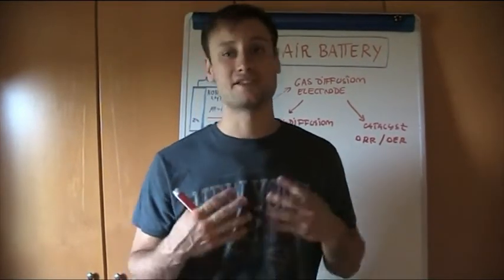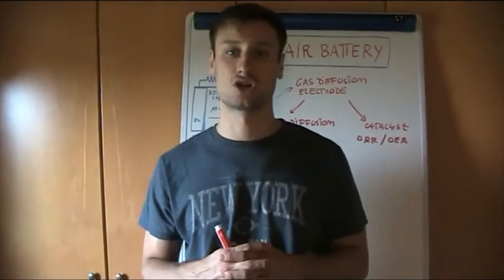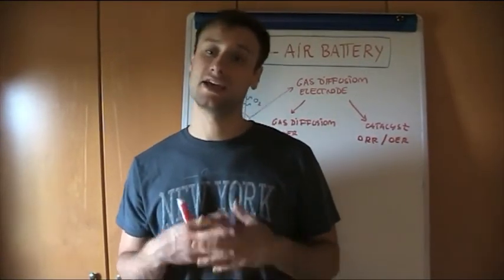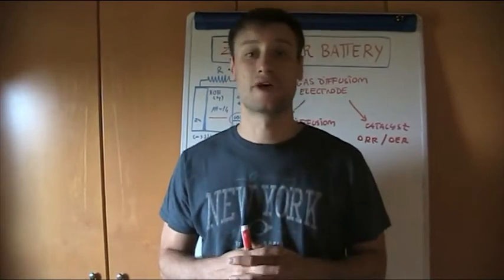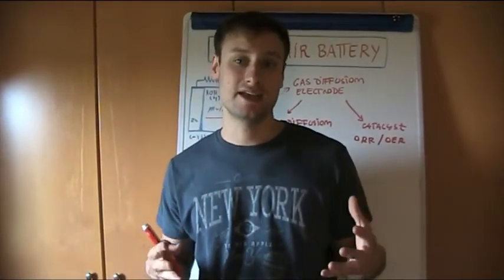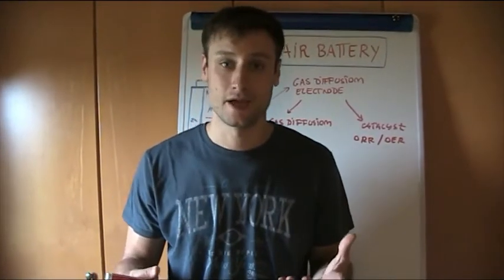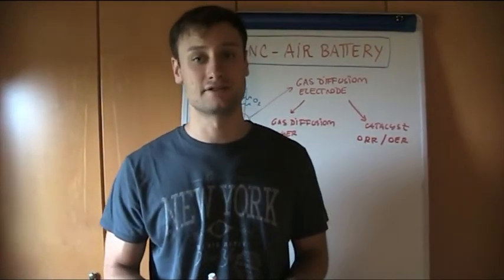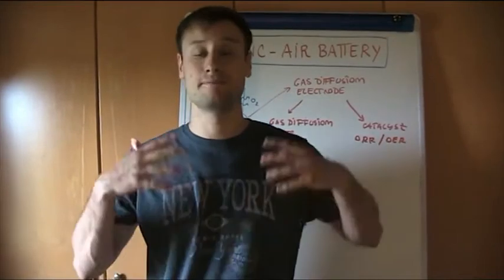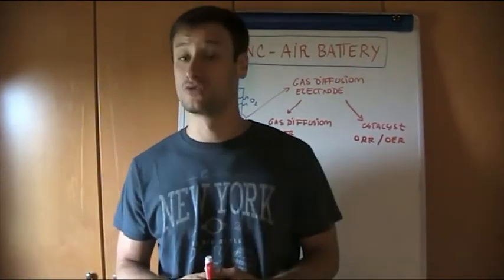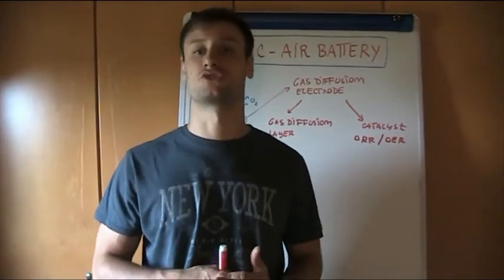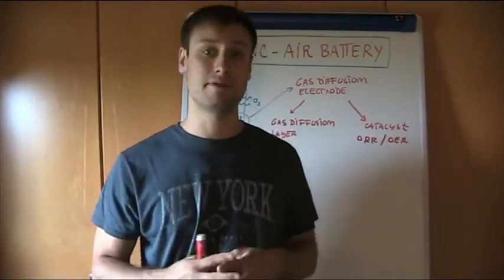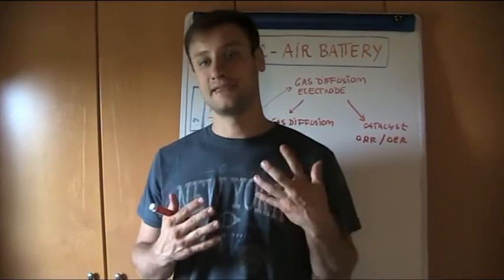And sometimes we can even see the use of Teflon, tetrafluoroethylene, as a binder, because in this way we are improving the hydrophobicity. So we are using something that is carbon-based, but with something polymer-based as a binder. Teflon is really hydrophobic. Let's remember the contact angle of water on Teflon. Teflon is a typical case of a superhydrophobic surface, since water rolls down without penetrating this material. And this is extremely important because we want to tune the management of water.